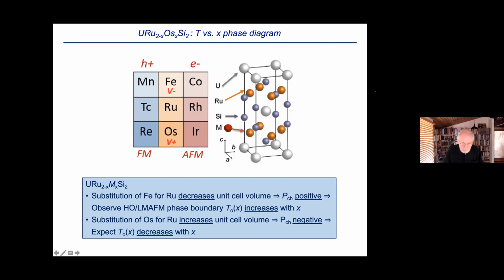So we found that one way we could interpret it early on was that the iron substitutions gave rise to a positive chemical pressure. And so then we observed that the hidden order temperature increases as you go through the transition, similar to what happens under pressure. And now if we were simply to assume that osmium would generate a negative chemical pressure, we would then expect that T0 decreases with osmium concentration.